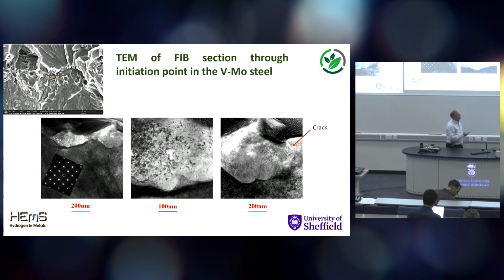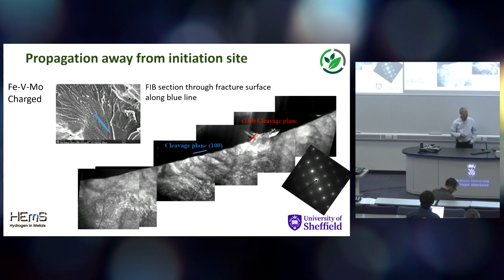Here's another example just on the other steel, again the same feature, so it's not just a one-off that we saw, multiple sections through these initiation sites. We always see these low dislocation density regions, then an abrupt boundary to a region of high dislocation density.